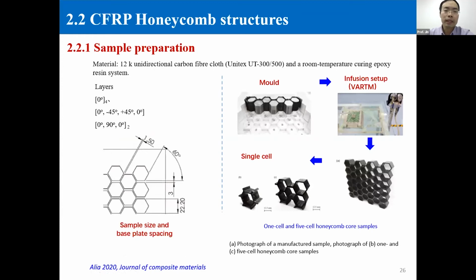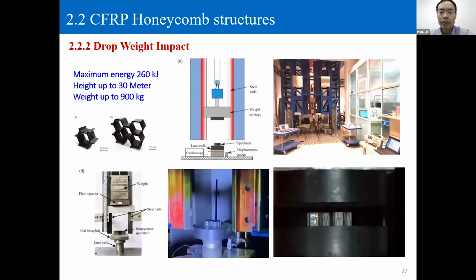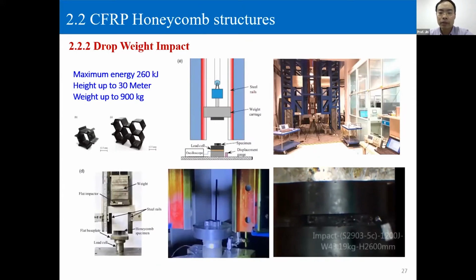And in the latest work, we also did both quasi-static and impact tests on those structures. Those specimens were made at Khalifa University, and my colleague Alia and Professor Cantoner made those samples, and I did the dynamic test using a drop weight. Initially, we focused on the energy absorption with different layers and different manufacturing processes. And my research focused on the dynamic loading rate on those structures.